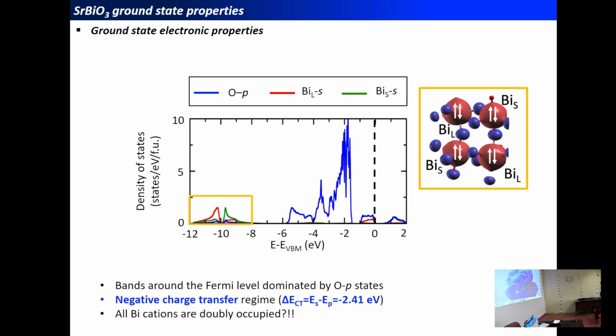Effectively, if we look at the projected density of states on the oxygen p states and on the s orbital of the two bismuth cations, we end up with an asymmetry of the electronic structure. Around the Fermi level, it is dominated by oxygen p states. So it means that we are in a negative charge transfer regime, meaning that the oxygen p states are above the relevant bismuth s states. Nevertheless, we see that we have an asymmetry of the electronic structure.